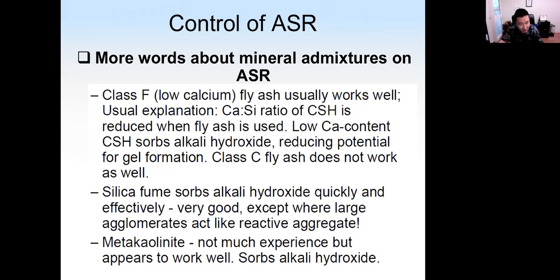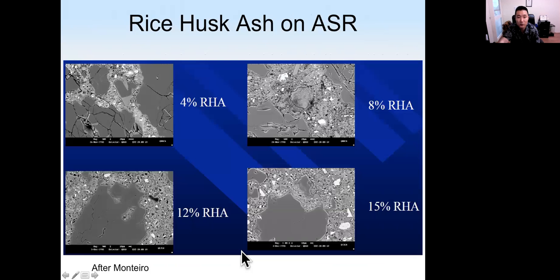Okay, other types of mineral admixtures such as metakaolin may also be working to reduce ASR. Even rice husk ash. Okay, here shows people using different dosage of rice husk ash to reduce ASR. You can see increase the dosage from 4% to 8% to 15%. We see less cracking due to ASR. Okay, so rice husk ash can also reduce the potential ASR.